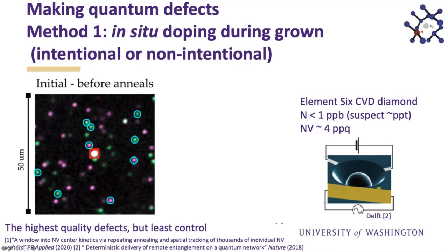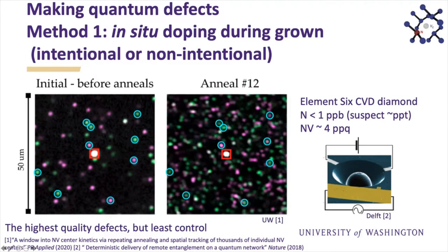Curiously, because we can look at these single defects, we can track them as we do things to the sample. So this is an example where we've heated up the sample and we can get more defects. We can actually form them from existing impurities inside the diamond just by heating it up. And we can learn something about the temperatures that they form and really get a fundamental understanding of the physics that goes into the formation of these defects. Okay. So these are the highest quality defects, but there's the least amount of control due to placement.